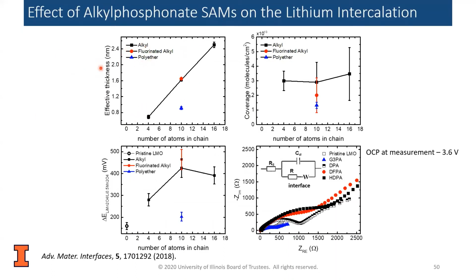And so this first plot right here is a comparison of the two-layer model calculations. And so we see as we increase the alkyl chain length, we get a pretty linear increase in thickness, which is good. That would suggest to us that the SAMs are standing up like they should. Then if we look over at the coverage, they all, in all respects within the error margins, have the same amount of coverage.